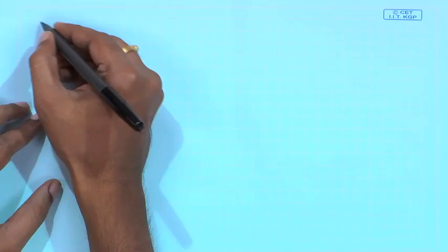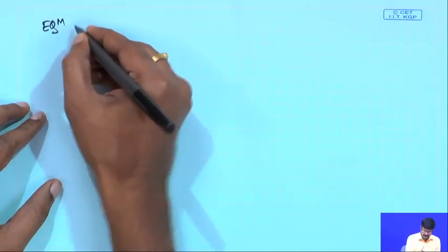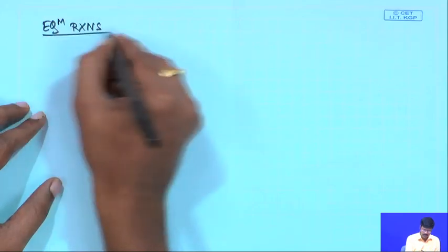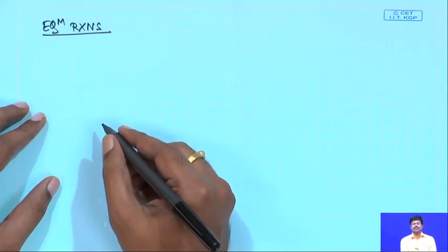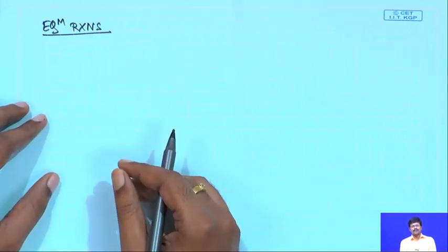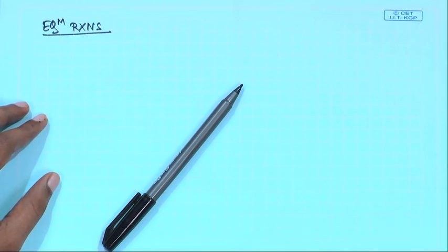Okay. So, now let us move on with this discussion to something else. We have talked about these reactions as equilibrium reactions, which needs no further explanation: you have to remove the water from the system. What happens if you do not remove water? What happens if you do the reaction in a closed system, where you do not remove any of the products? After some time, when enough product has developed, the backward reaction will be fast enough and depolymerization will take place. So, an equilibrium will be reached.